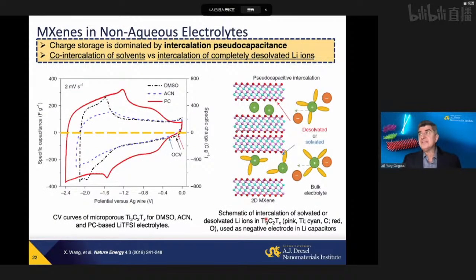The same things happen in organic electrolyte. This is now lithium TFSI in DMSO, acetonitrile, and propylene carbonate. What we found when we studied this system, the results were counterintuitive. Highly conducting acetonitrile solutions, which in a conventional carbon supercapacitor should give the highest performance, actually gave the lowest capacitance, the area under the cyclic voltammogram.